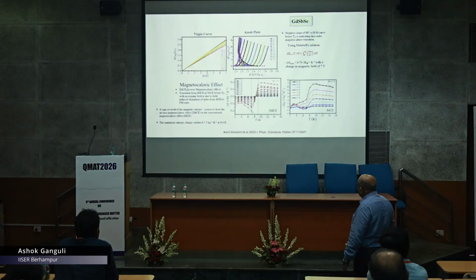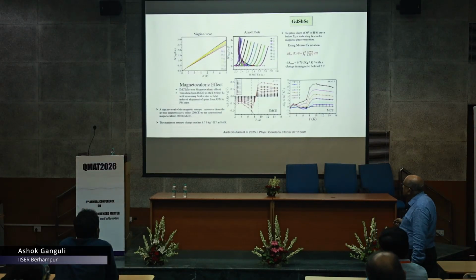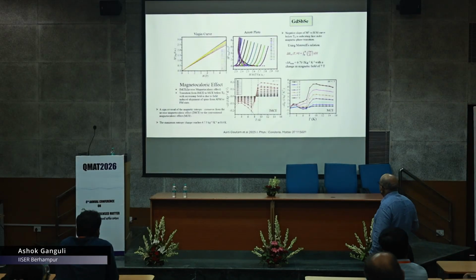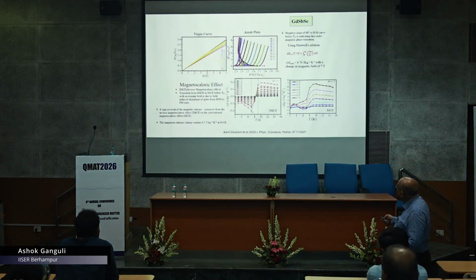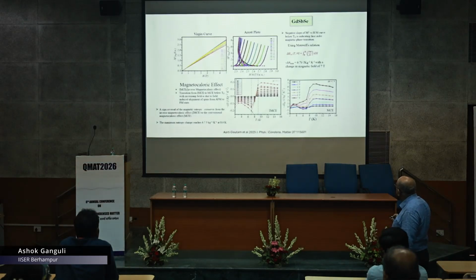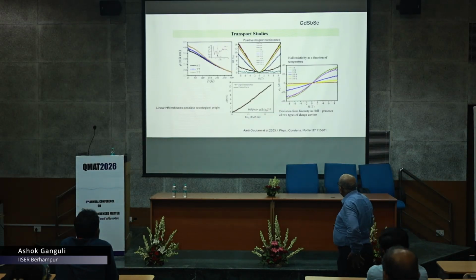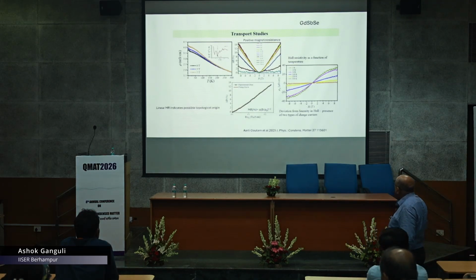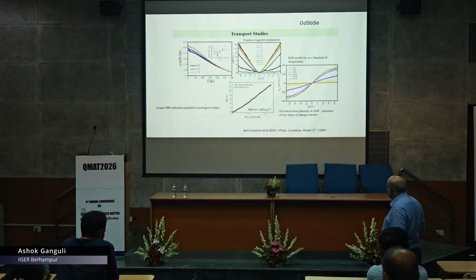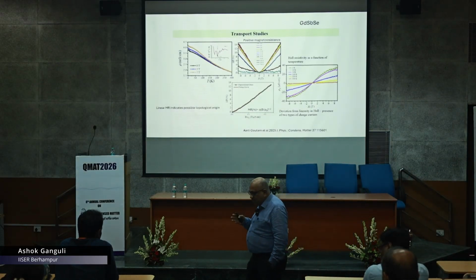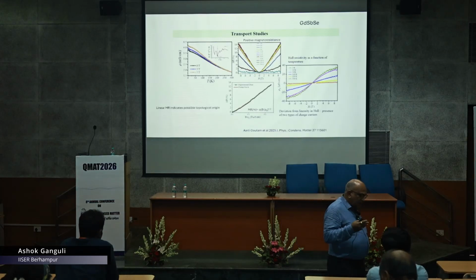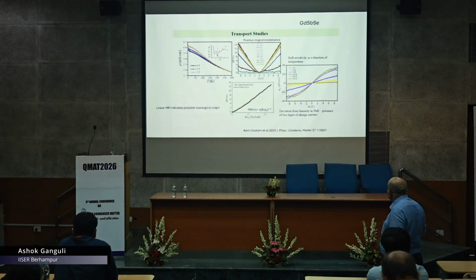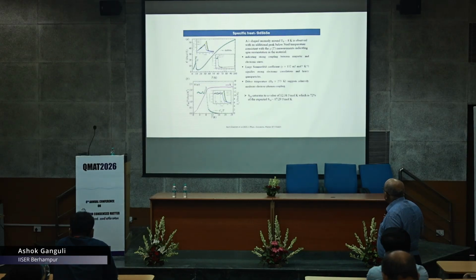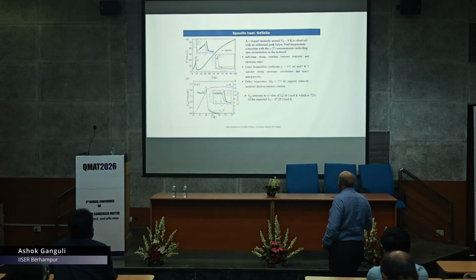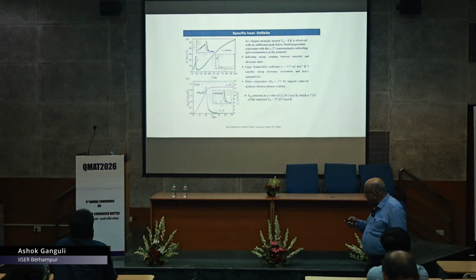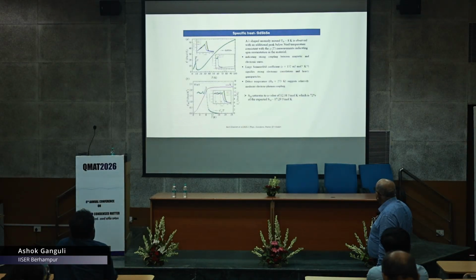You can measure the magnetocaloric effect, and you can see the changeover from the inverse magnetocaloric effect to the normal magnetocaloric effect. And you can look at the Arrott plots. It's a first order phase transition. You can also look at the magnetoresistance, and you can see positive magnetoresistance in this compound. The Hall measurement shows a deviation from linearity, so you can try to fit it to multiband type properties. We can measure the specific heat, and we have a very large Sommerfeld coefficient, which suggests strong coupling, and you can measure other properties.